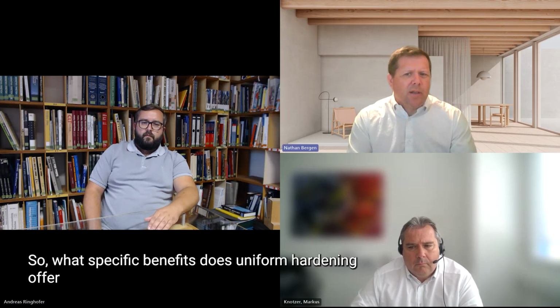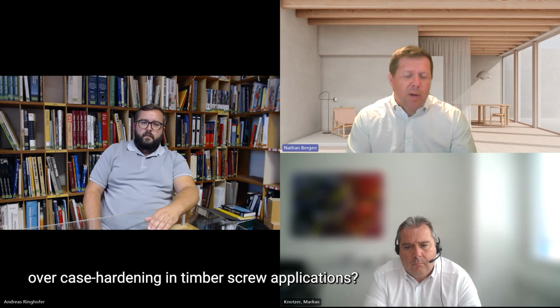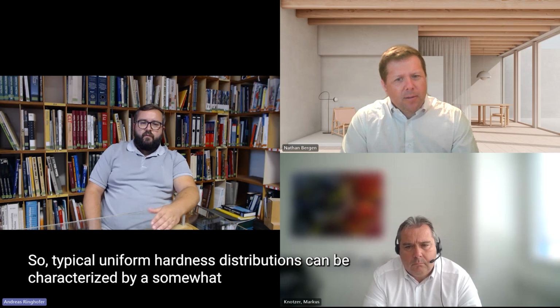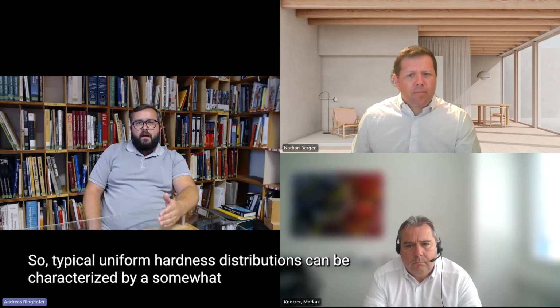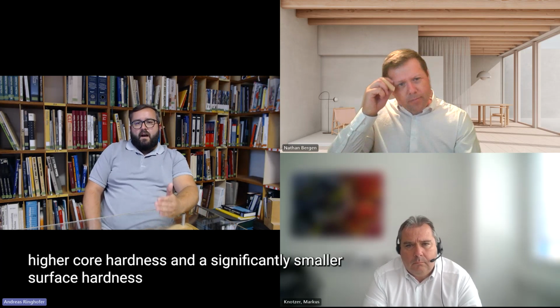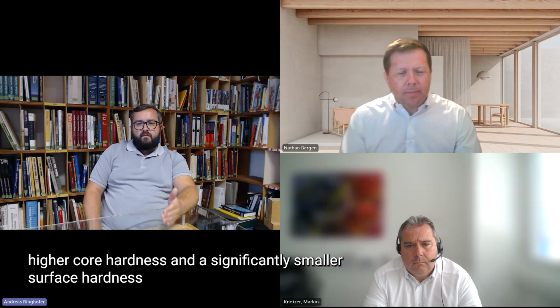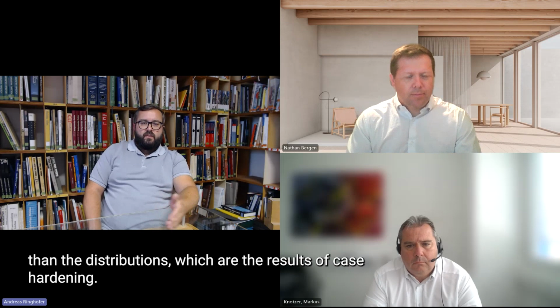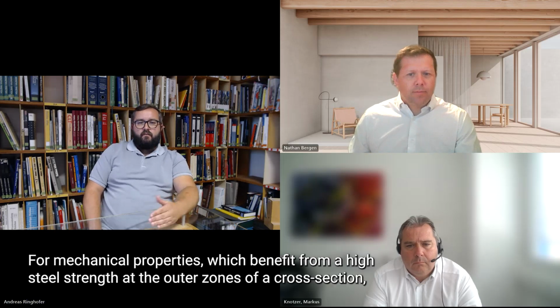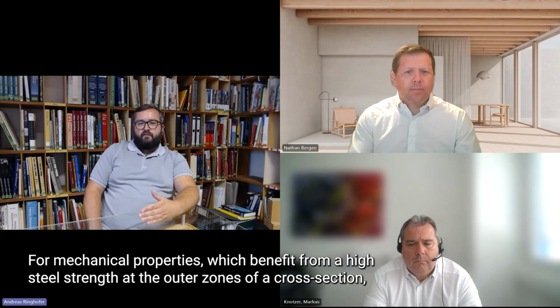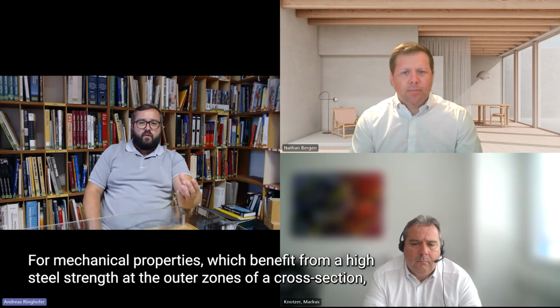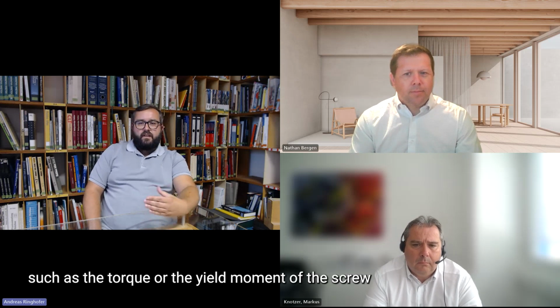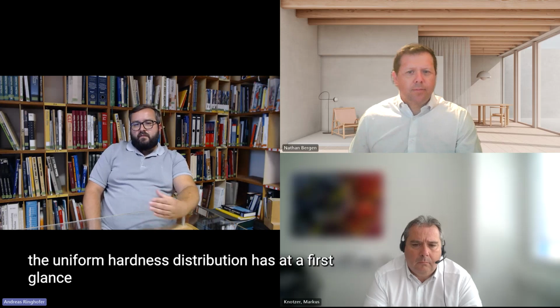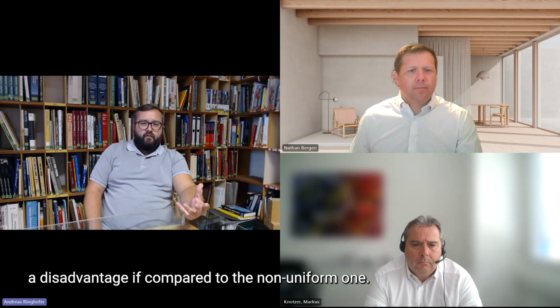So what specific benefits does uniform hardening offer over case hardening in timber screw applications? So typical uniform hardness distributions can be characterized by somewhat higher core hardness, yes, and a significantly smaller surface hardness than the distributions which are the results of case hardening. For mechanical properties which benefit from high steel strength at the outer zones of the cross-section, such as the torque or the yield moment of the screw, the uniform hardness distribution has at the first glance, let's say, a disadvantage if compared to the non-uniform one.